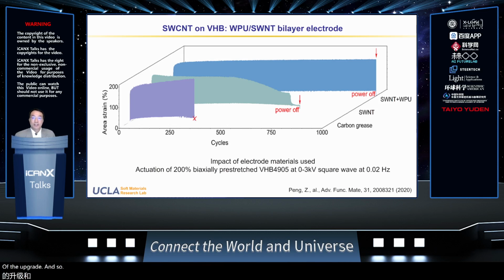actuator. Shown here is what happens if we use carbon grease, which is very convenient to use and consistently delivers high actuation strain. With the carbon grease electrode, when you operate to a certain number of cycles, you will see breakdown, so in a way, a terminal failure of the actuator.